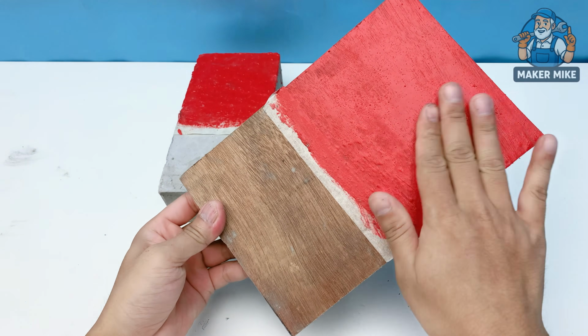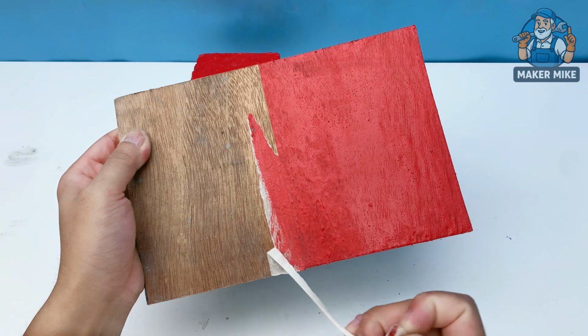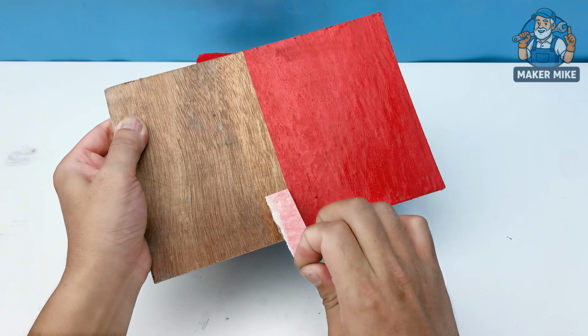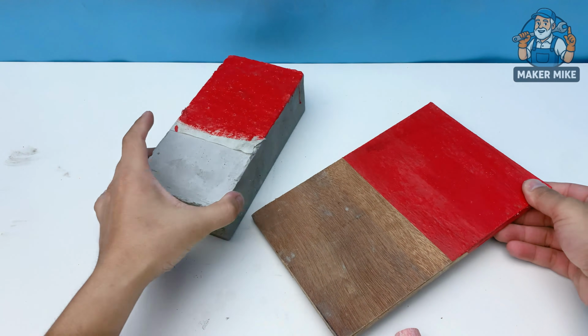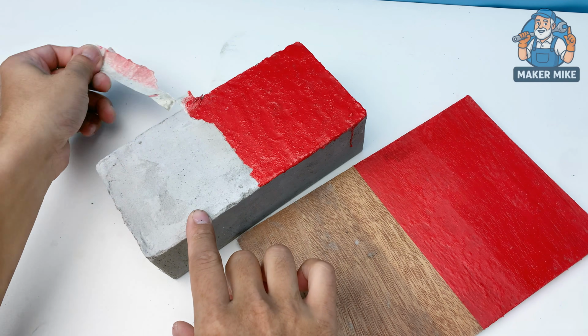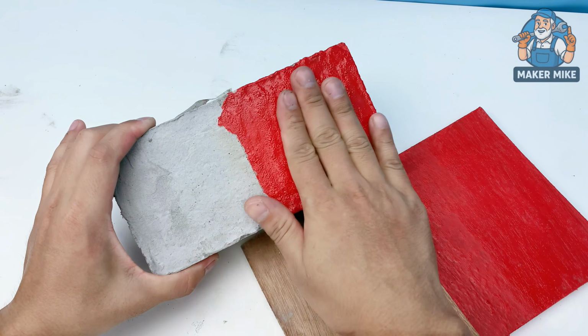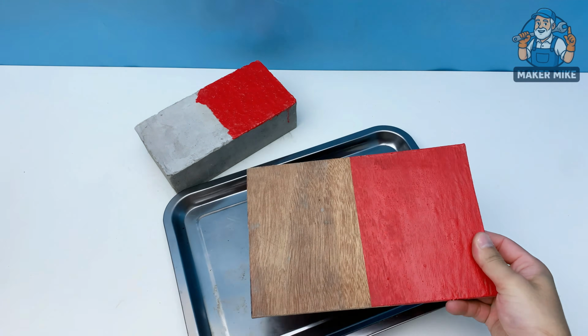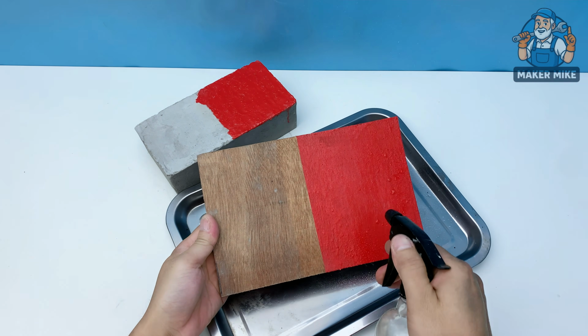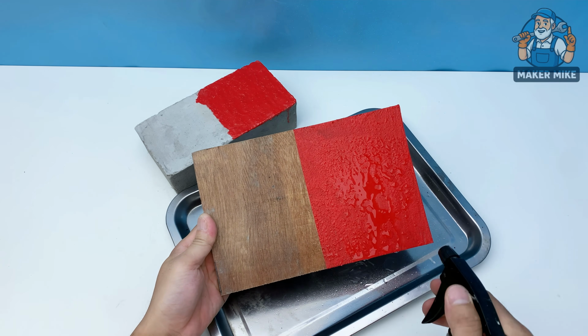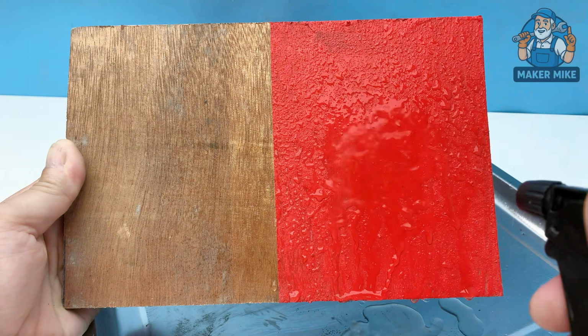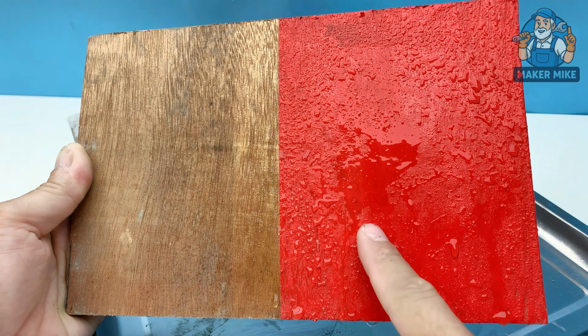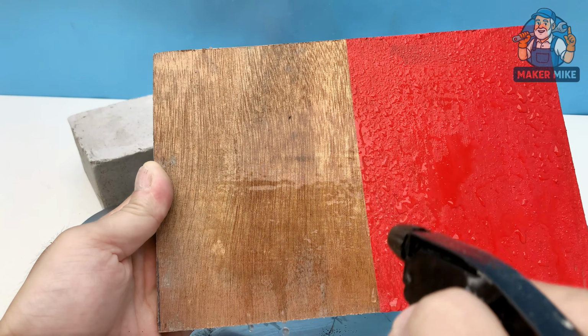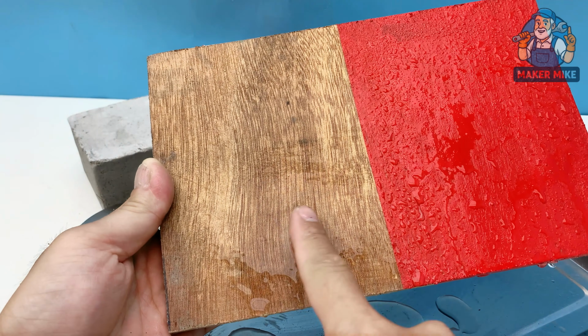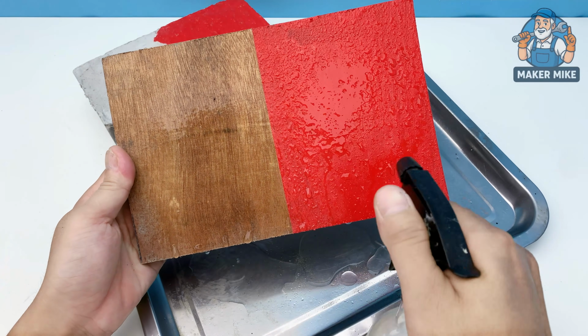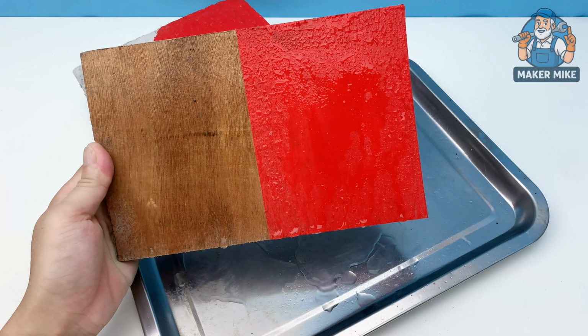Now, return to the wooden board and the brick that have dried. This is the time for the real test. Spray water onto the wooden board. You can see that the surface coated with the mixture makes the water run down in droplets without soaking into the surface. The water on the coated surface reacts quite differently compared with the untreated part. This shows that the coating has created a water-blocking film on the wood surface in this test.